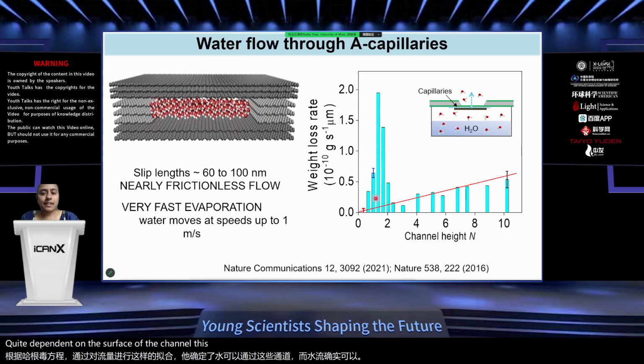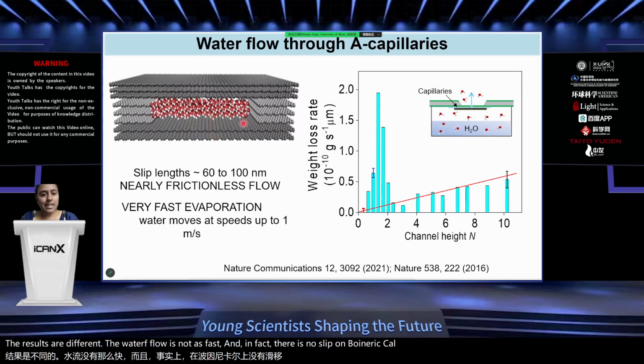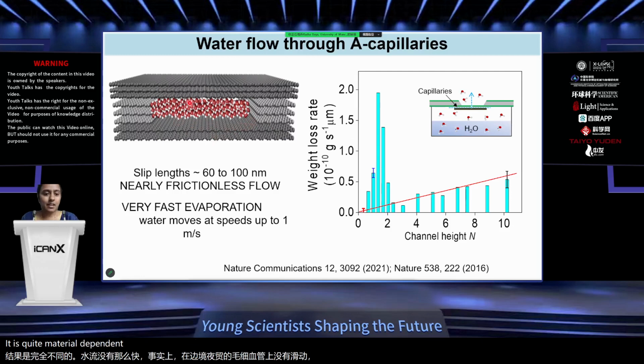These results are for graphene capillaries. If we do the same measurements with boron nitride capillaries, the results are completely different. The water flow is not as fast, and in fact, there is no slip on boron nitride capillaries. So the property of the water flow is quite material dependent.